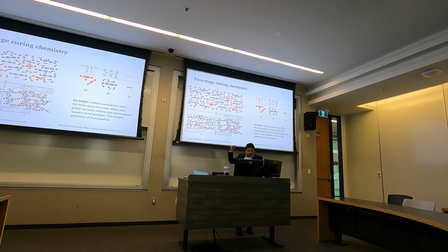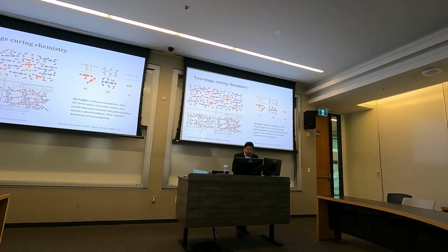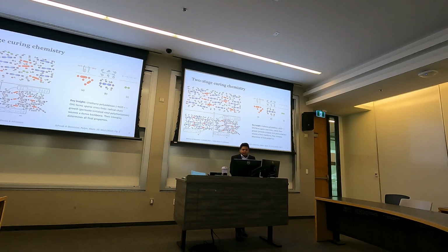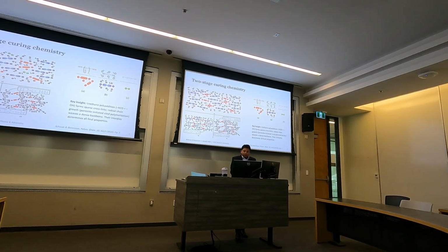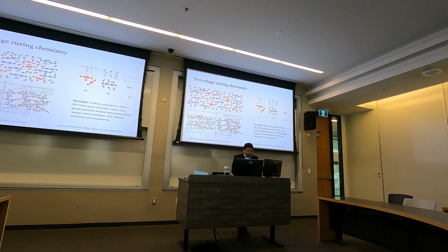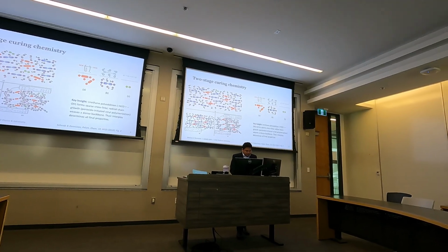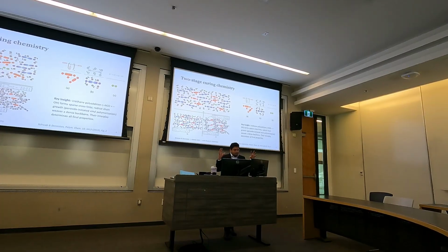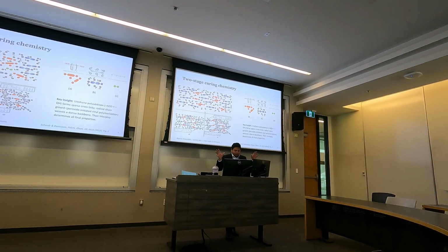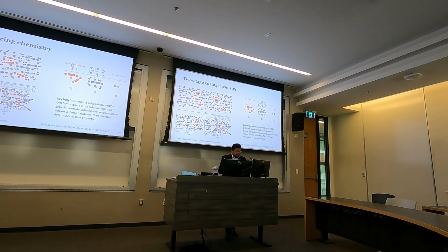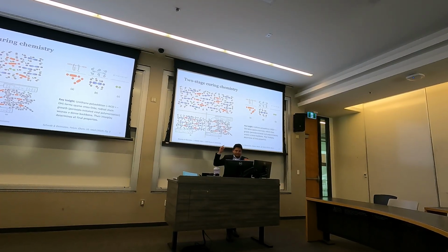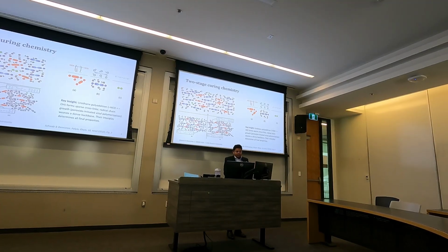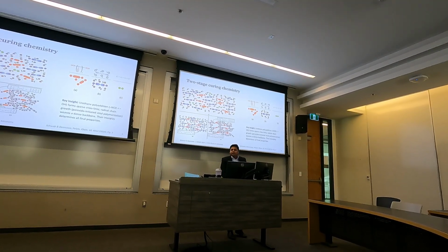On the right hand side, you see the 3 molecule types and their chemical structure in a coarse-grained representation: PMDI isocyanate, an unsaturated polyester polyol with styrene comonomers, and peroxide initiators. The key point here is that the urethane forms a sparse cross-link network between polyol chains, while the radical polymerization creates this dense network. Together, they determine the final thermal and mechanical properties of the material.